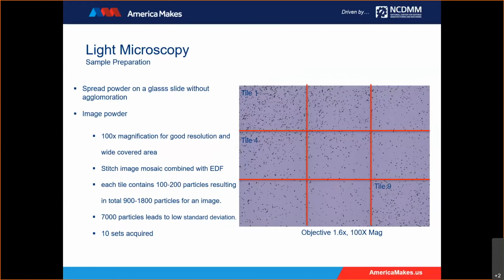Each tile contains about 100 to 200 particles. In an area like this with 9 tiles, we can get from 900 to 1800 particles for an image. We've done some experiments and learned that we need to collect at least 7,000 particles to get a low standard deviation when measuring our particle size distribution. So we acquire 10 sets of these in a mosaic.